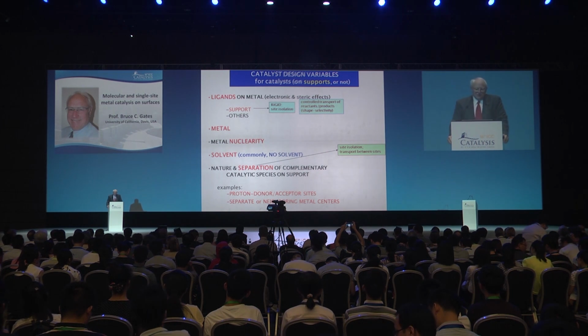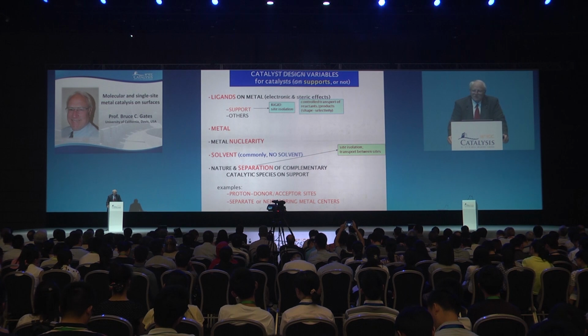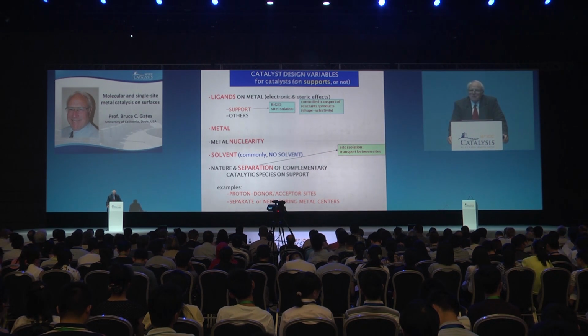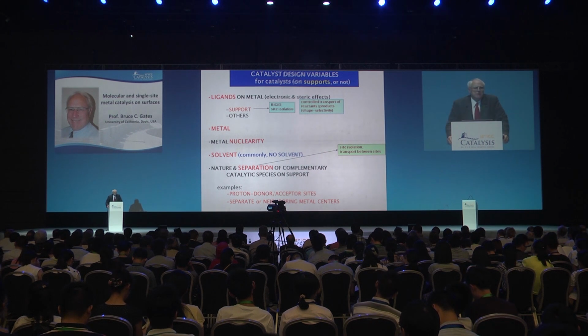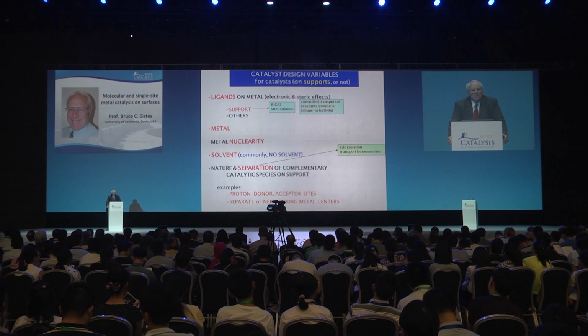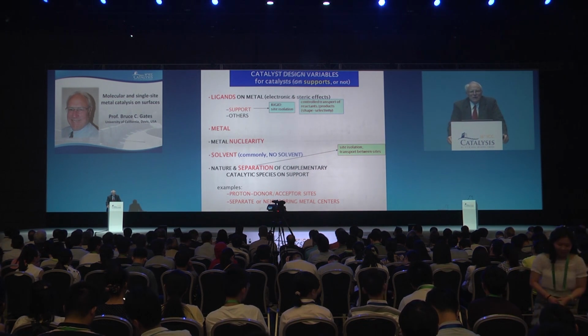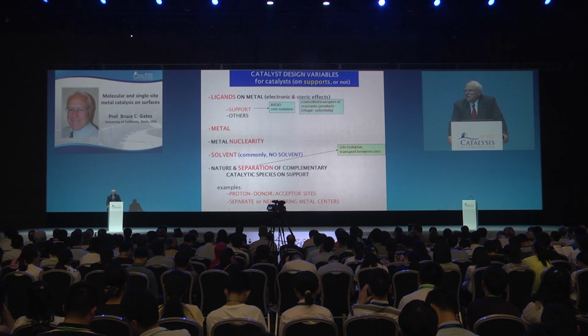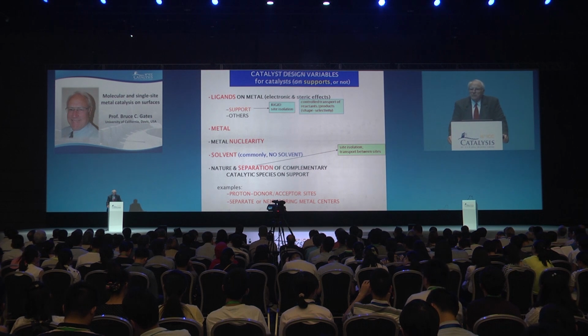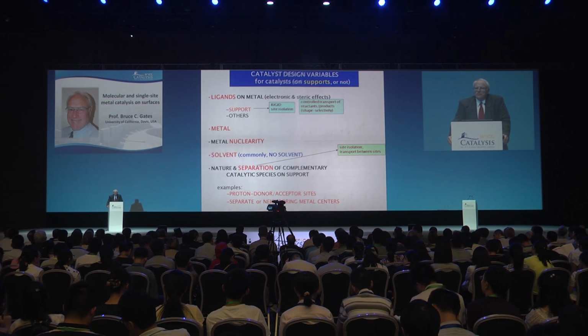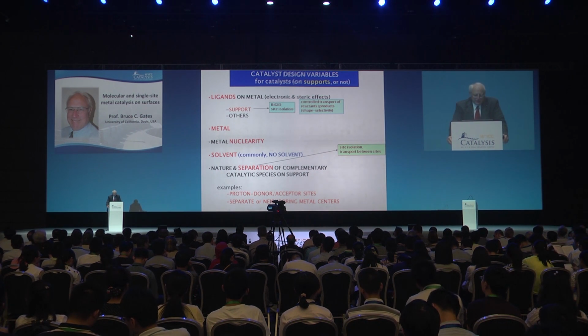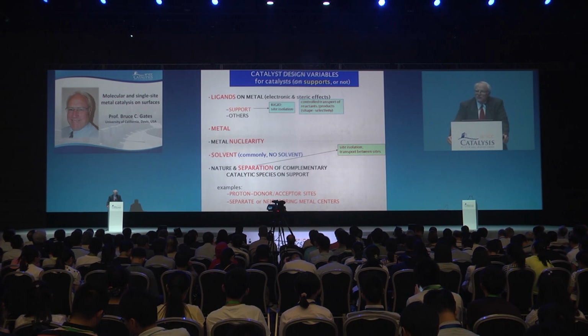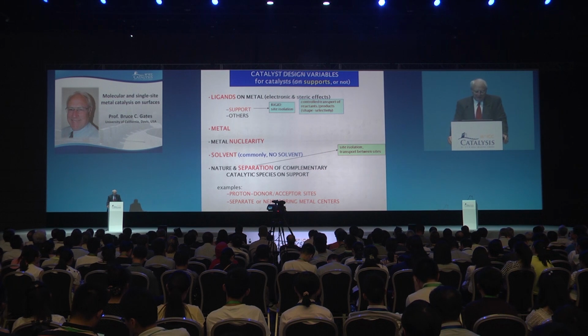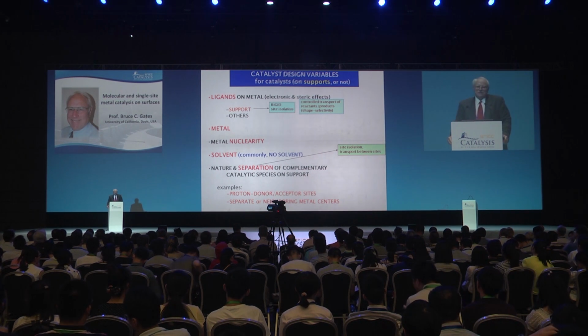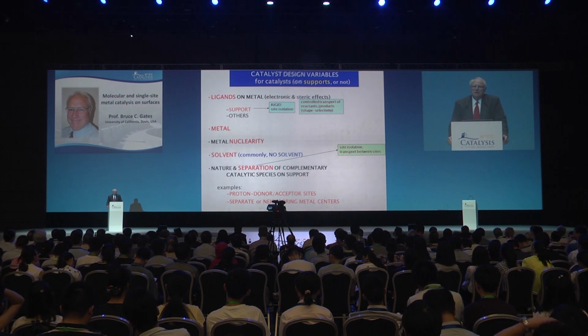The solvent's important, but for us working with surfaces, usually not. We don't use one. But think about that. The solvent in homogeneous catalysis often plays an important role, and it complicates matters. Solvent can coordinate with the metal. So in a way, we can do the surface organometallic chemistry more cleanly and more simply than one can do it in solution because we remove the complexity of the solvent. And then the issue of the separation of the sites harkens back to bifunctional catalysis. One thinks of things like tandem catalysis. And there are, again, lots of opportunities for catalyst design by strategic placement of the species on the supports.